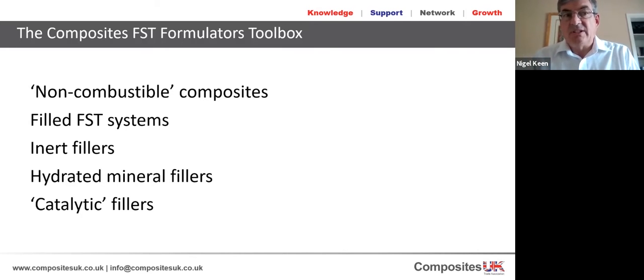The next stage really is to, as I said, minimize the organic content and put lots of filler in. Fillers are very useful for fire, smoke and toxicity. They reduce the amount of stuff that is there to burn. So simply having a high amount of inert filler in your system will be helpful. The drawback is, of course, that you can't then have a high fiber content, because you need the resin matrix to wet the filler as well as the fiber. So your fiber content will drop, which may not be a problem for certain applications, things like worktops, where you've got something that's fairly thick and stiff, and that's its primary purpose. It's not too much of a problem to have a lot of filler in there.